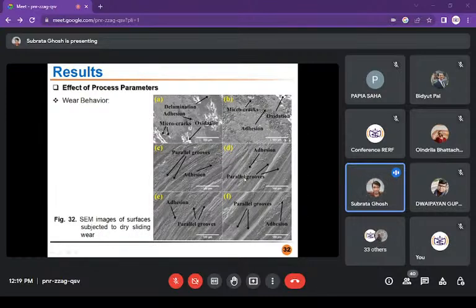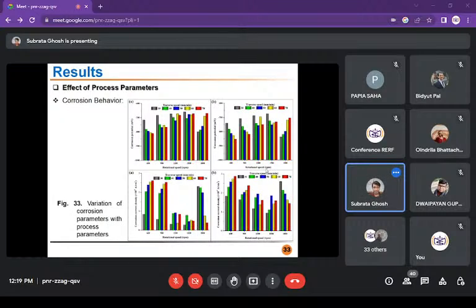are there. So these particles will come out and act as an abrasive. Because of that, this kind of wear looks like abrasive wear. In wear testing, there will be a pin rotating over the surface. So if abrasive comes in between the pin and the workpiece, that will create the wear. So this kind of wear is happening.